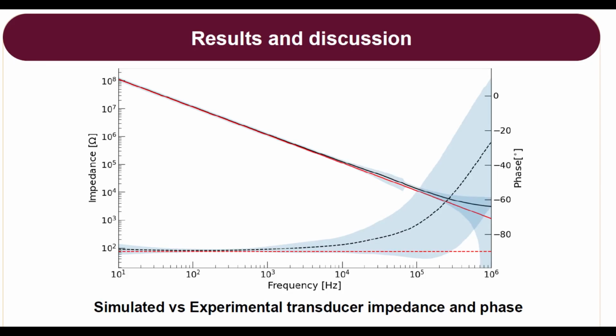The results obtained in this section illustrate the average behavior of the fabricated transducer compared to a simulation conducted using COMSOL Multiphysics software. As demonstrated, the simulation, represented by red curves, shows an ideal capacitor behavior, while experimental results, represented by black curves, exhibit real capacitor behavior with parasitic effects at high frequencies. However, at low and mid frequencies, simulation and experimental behavior align, indicating proper transducer functionality. The standard deviations, indicated by blue shadows, maintain relatively low values, reflecting the reproducibility of the manufacturing process.